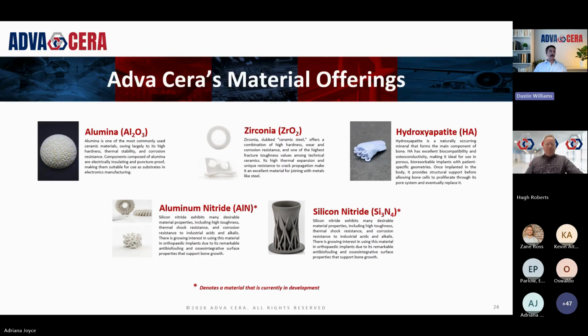Next on the list, and also next from a volume standpoint of what we produce, is zirconia. Zirconia is a very tough material. It can be referred to as ceramic steel almost. It's got some great hardness, very high fracture toughness, and resistant to crack propagation. It's a great choice for structural components, more applications where mechanical reliability is critical. And it interfaces really well with other materials, metals. There are some nuances to printing zirconia as compared to alumina, but our team works with it quite frequently.